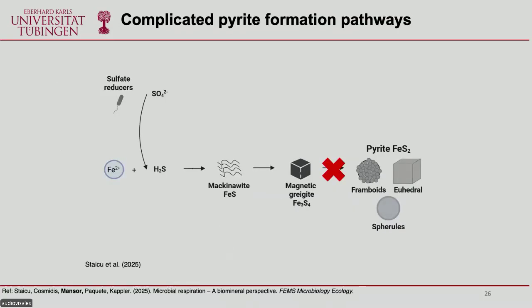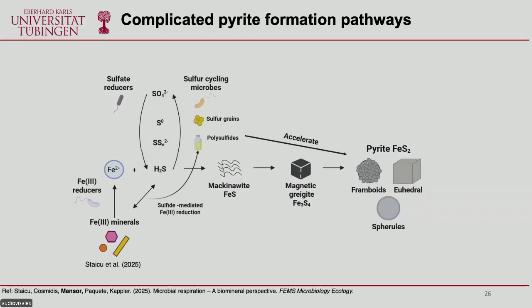But then looking at the literature and trying to piece together what people know, actually it's not so easy. You don't just need sulfate reducers and iron to form pyrite. You need more than that. It's much more complicated because you need all of these different processes. You need iron(III) minerals that can be reduced by iron(III)-reducing bacteria. You need all these different sulfur intermediate species. And then following the combination of all these processes, you can form pyrite. And this is really challenging to replicate in the laboratory because you need all these different microbial species and intermediate species, and you need to track all of them.